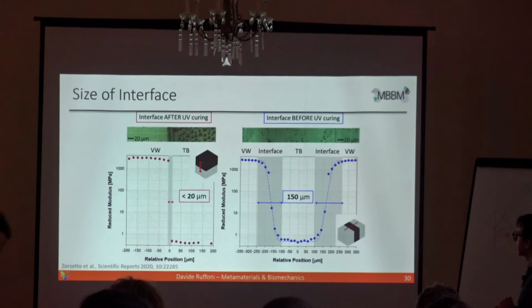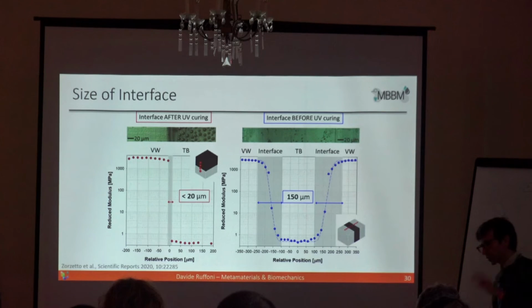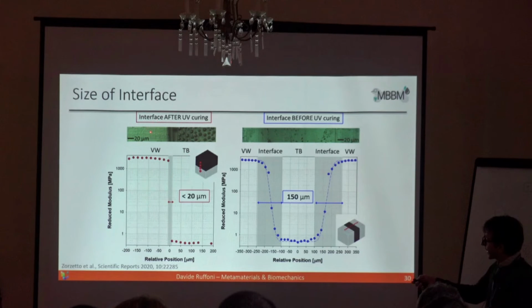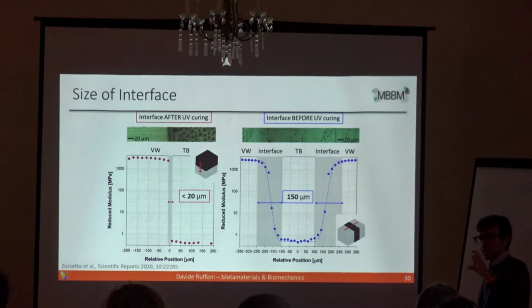So, very simple composite. To answer the first question, we did nanoindentation, and we measured the transition in reduced elastic modulus when going from stiff voxel to soft voxel, for the case when the interface was formed after UV curing, and what you see is a very sharp transition. Within less than 20 micrometers, you have a transition between the stiff voxel and the soft voxel, and these dimensions are comparable to the voxel size, okay?